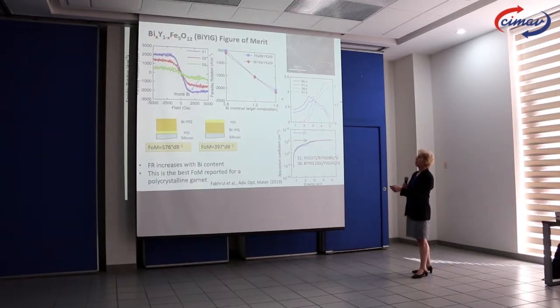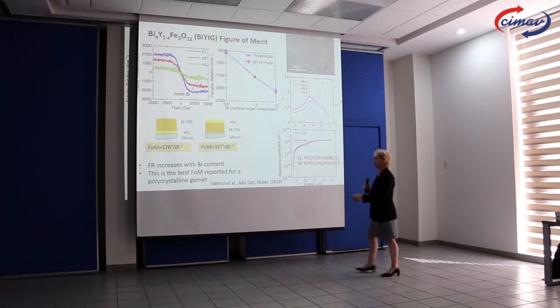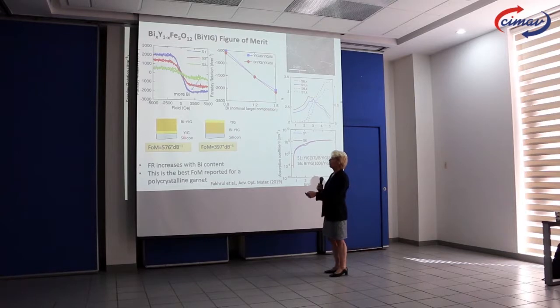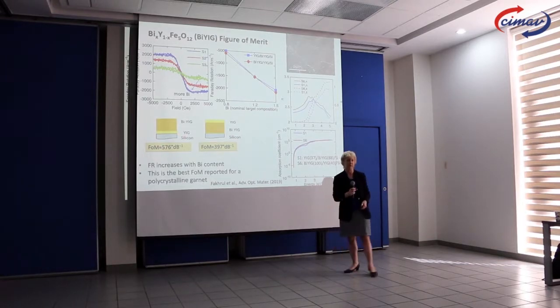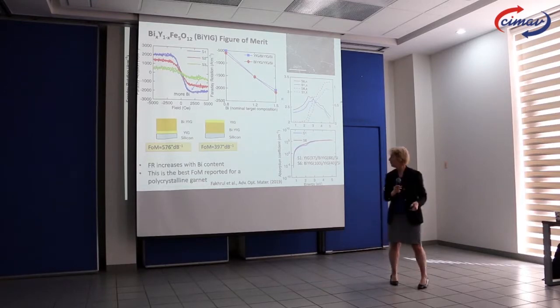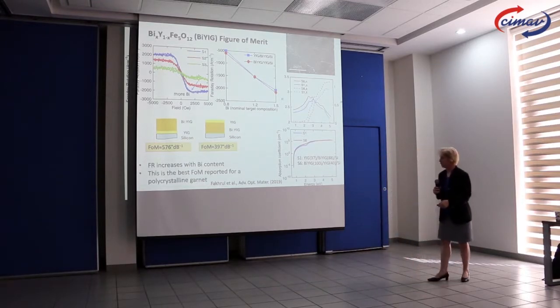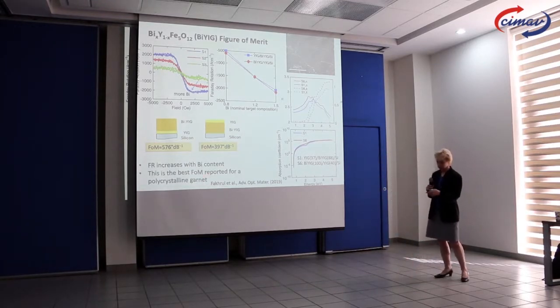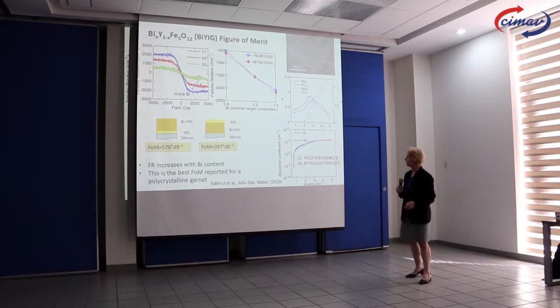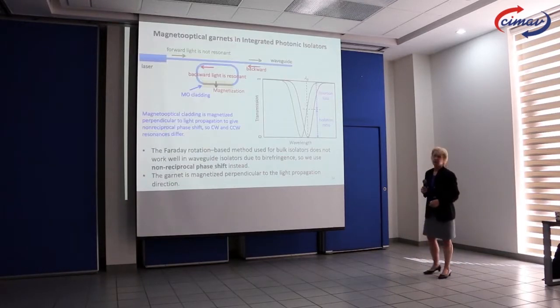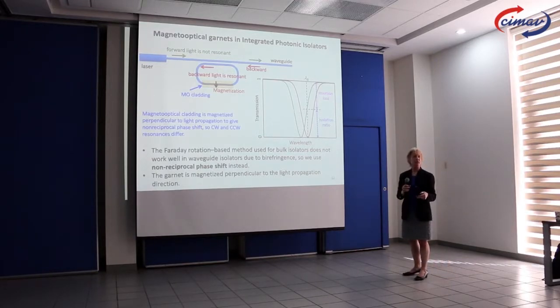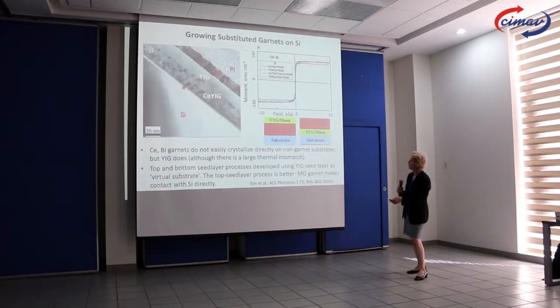We can also make bismuth YIG on silicon the same way. And these things have very good figures of merit. So it can be hundreds of degrees per decibel, so very good material for these optical isolators. This is actually the best one reported for a thin film, polycrystalline thin film. So now we've got to make a device. So how is the device going to work? It turns out that the method I showed you before, let me just step back to that.